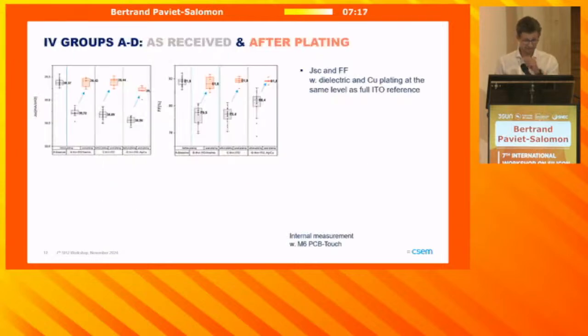So let's dive now into the IV of those devices. We start with the JSC on the top left graph. As received, those devices feature a lowish JSC because the thin ITO is not a good TCO. But as expected, once we completed them with the masking layer and the plating, we fall back on a JSC which is perfectly on par with the reference featuring full ITO and full silver.